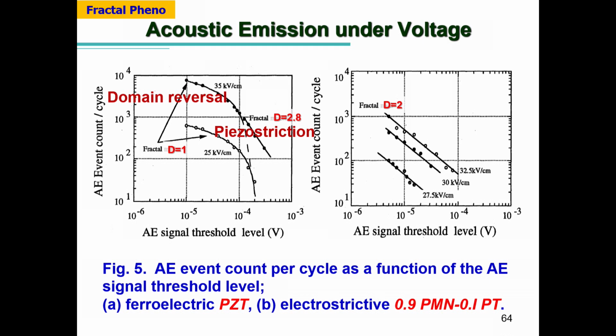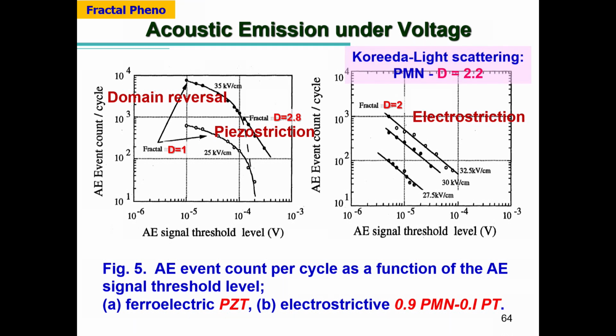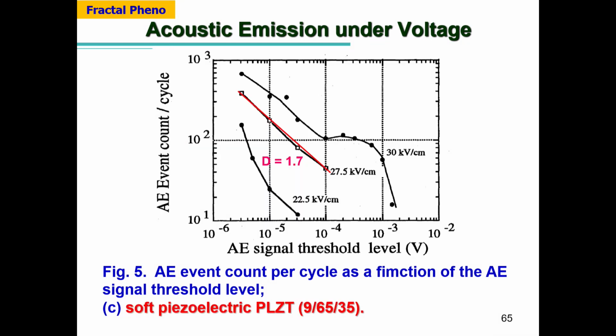And the interesting situation is PMN-PT, okay? PMN-PT is exactly 2, okay? And you remember Koreeda's data for PMN, the fractal dimension is 2.2. Ours is slightly different, but rather close. So the electrostrictive type is roughly around 2. And this is a soft PLZT. So some of the slope gives a fractal dimension of 1.7.